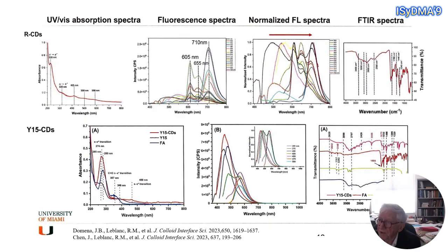So two other preparations have been shown. For the red carbon dots, we use a derivative of porphyrin, and in that case, we're able to see the luminescence at 700 nanometers. And that's very important because in oncology, we don't have any autofluorescence due to particles in the blue region. And many of the carbon dots that have been prepared with different plants, for example, present mainly blue emission, and that means not too good for oncology.